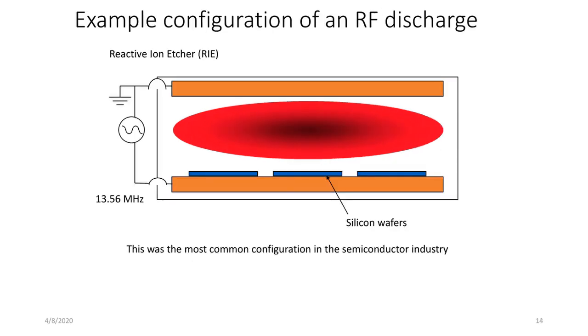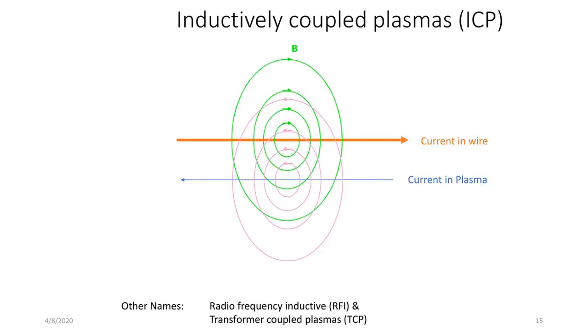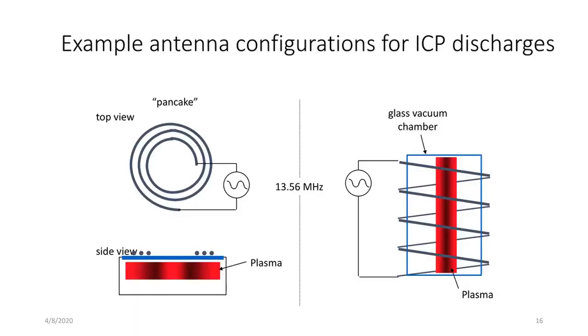In an inductively coupled plasma system, you have a coil. To show this more clearly, this is how an inductively coupled plasma torch usually looks. You have a vacuum chamber, a glass chamber; the glass here is quartz. When you apply a frequency, say 13.56 megahertz, or usually 4 megahertz, 5 megahertz, or 6.5 megahertz, across this coil, an induction effect is caused on the gas passing through the chamber in between.